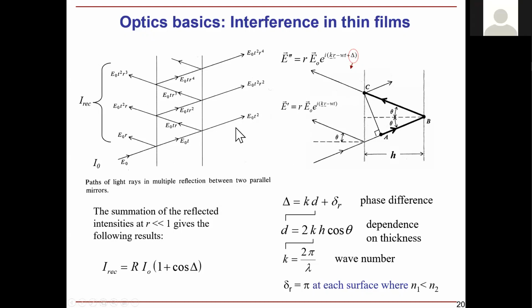Anyway, the point is that if you measure the reflected light here, you are going to measure something which is a function of the thickness and the refractive index. So if you change the thickness and the refractive index, you have two means of changing what is going to be reflected from the film, right? This is very important because this relates to the optical properties of polymer coatings, and to studying similar phenomena.